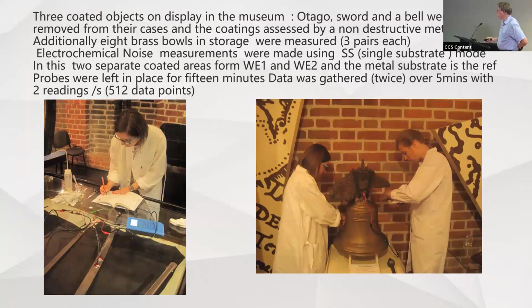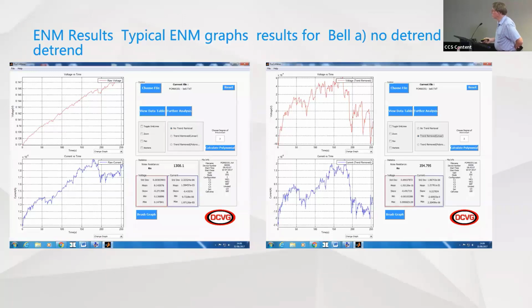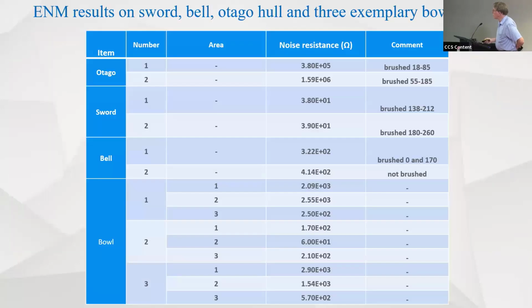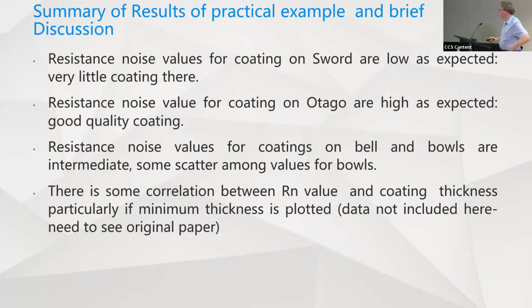So these are the measurements being made in situ with the probes attached, getting some idea of the state of the coating. And this bit of work was quite successful. That's not the greatest of plots, but it does show the sort of things that were done. You need to do the trending on the data set. And then we got all these values of resistance from the various items, and essentially the values varied, not big. There's quite a few small values, but we could see that the sword was pretty low. We knew it had a fairly low protection on it, probably a bit too low. They would be recommended to put a second coat on there. The Otago was fine, high enough, good quality coating on there. The bell and the bowls were somewhere in between.